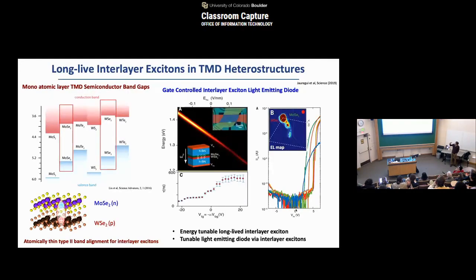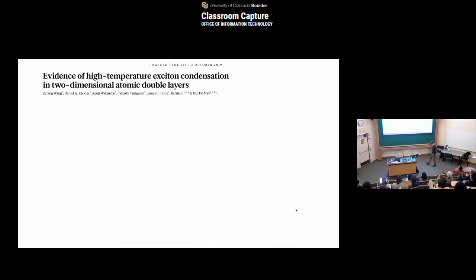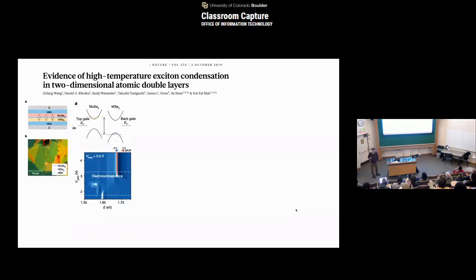But here you can see that, all right, it seems we can generate a reasonably long-lived interlayer exciton. There are actually even further efforts in this community. A few years ago, around a similar time, our colleagues, or the competitors in some sense, at Cornell actually demonstrated an even cooler demonstration. Here, the group of Kin Fai Mak and Jie Shan made a very similar device to the one I showed you, but they actually went one step further. Instead of making the PN diode I just made, they slid a very thin layer of boron nitride in between. So they made the separation further, right?